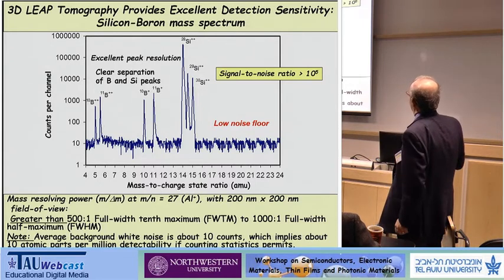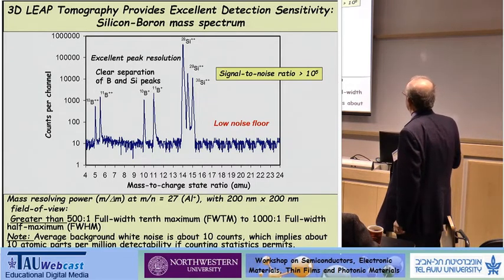And here's a simple example for a silicon-boron alloy. And you can see the 3 isotopes of silicon here in the doubly charged state. You see the 2 boron isotopes in the singly charged state. And here you see boron in the doubly charged state. And if you look at the background here, this is counts per channel.